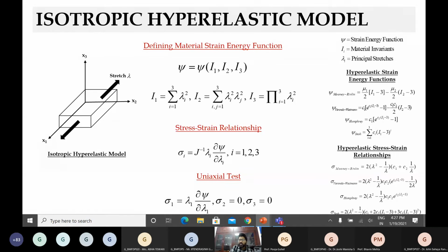So some have achieved correlation of, let's say, 0.9, some have achieved more than 0.95, but it also differs from one soft tissue material to another. So these are some of the hyperelastic stress strain relationships which were being developed through time, and none of this were developed by me. So these are all literature based, and these are standard norms for characterizing or giving any information to a finite element model that this is what I've found out from my soft tissue test, tensile test or surrogate test. Please compare.